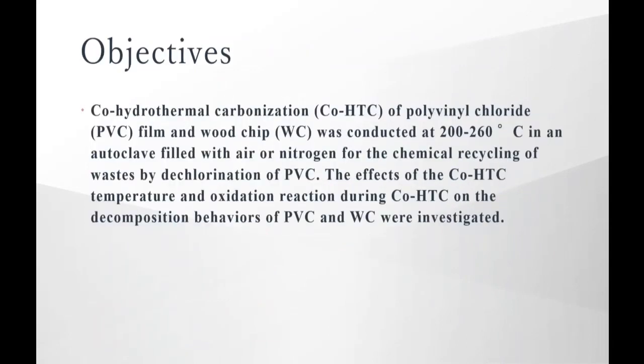Objectives of this research are as follows. Co-hydrothermal carbonization of polyvinyl chloride film and wood chip was conducted at 200 to 260 degrees C in an autoclave filled with air or nitrogen for the chemical recycling of waste by dechlorination of PVC. The effects of carbonization temperature and air oxidation reaction during co-hydrothermal carbonization on the decomposition behaviors of PVC and wood chips were investigated.